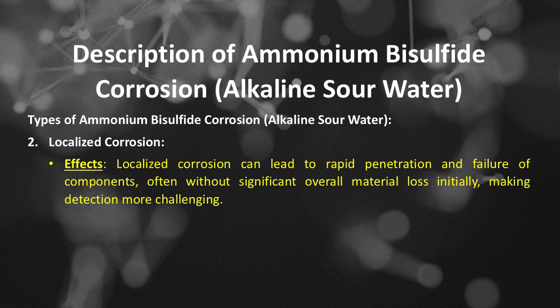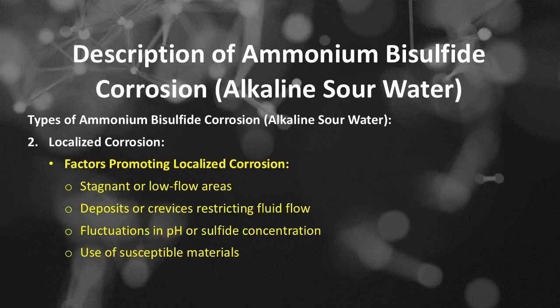Localized corrosion can lead to rapid penetration and failure of components, often without significant overall material loss initially, making detection more challenging. Factors promoting localized corrosion include stagnant or low-flow areas, deposits or crevices restricting fluid flow, fluctuations in pH or sulfide concentration, and use of susceptible materials.